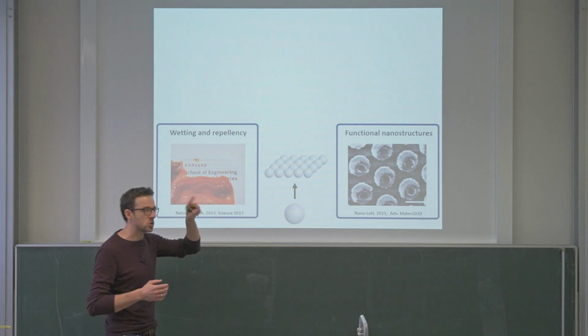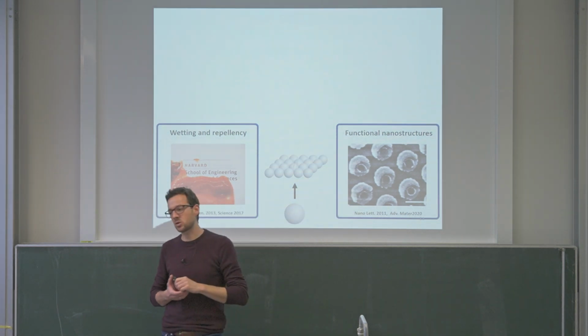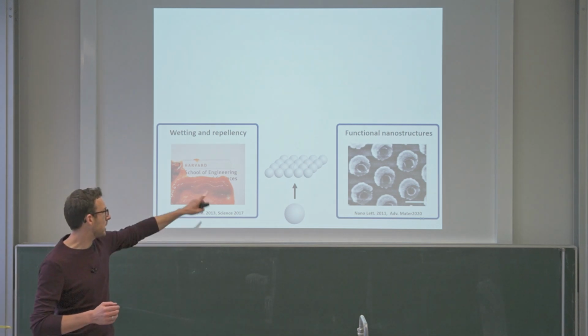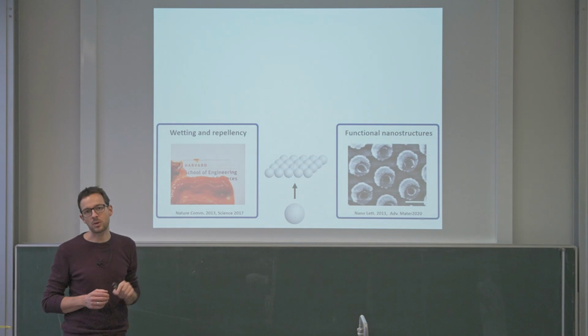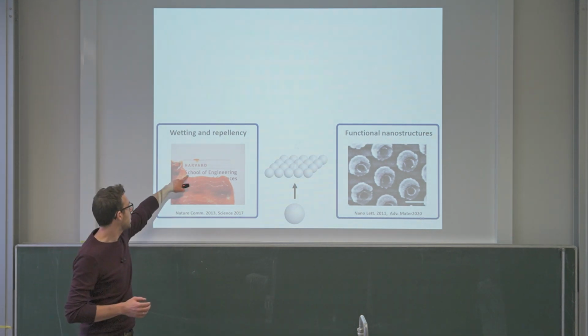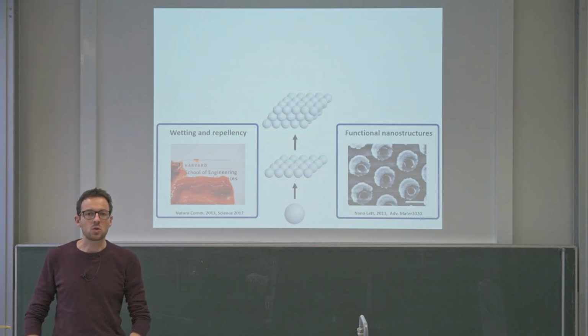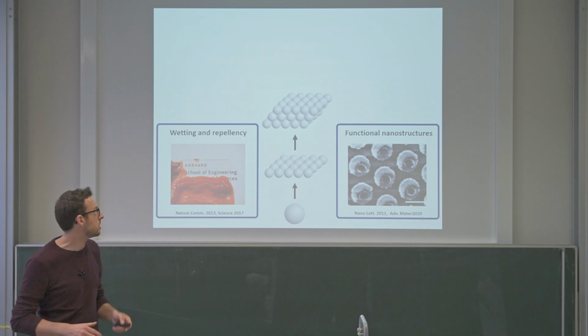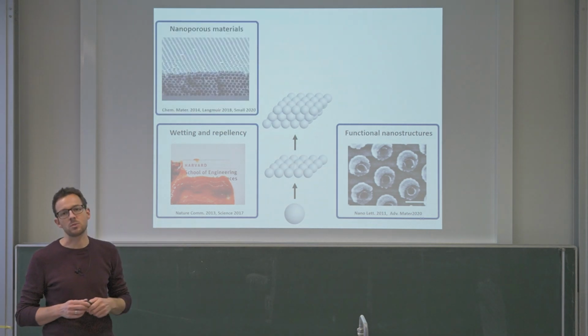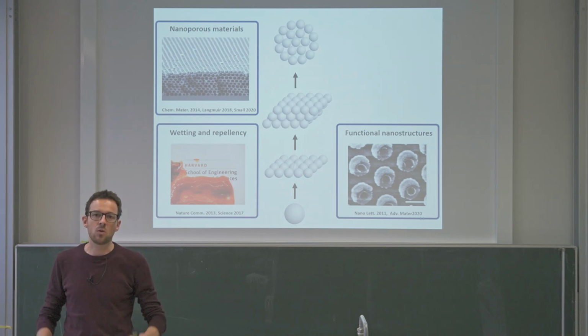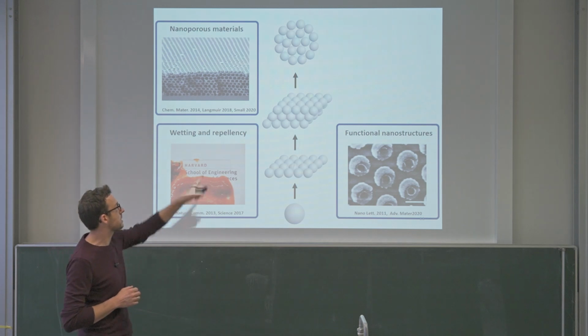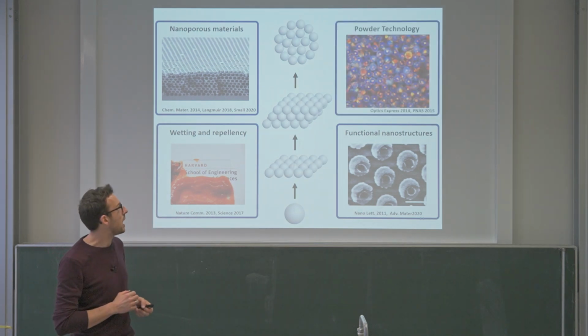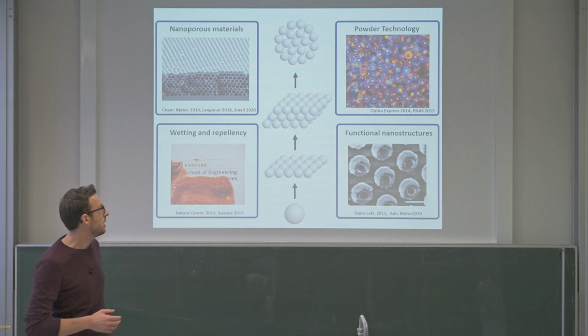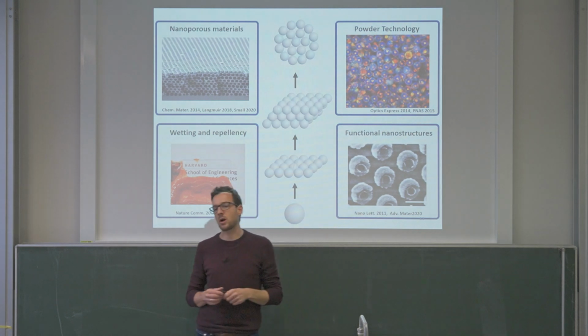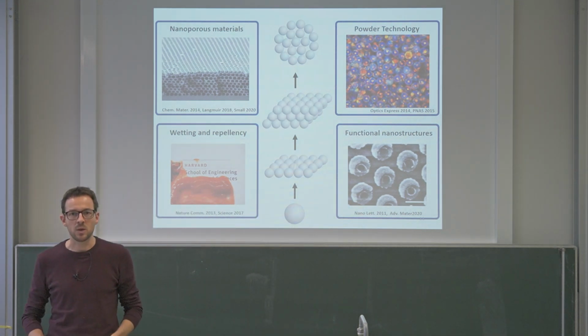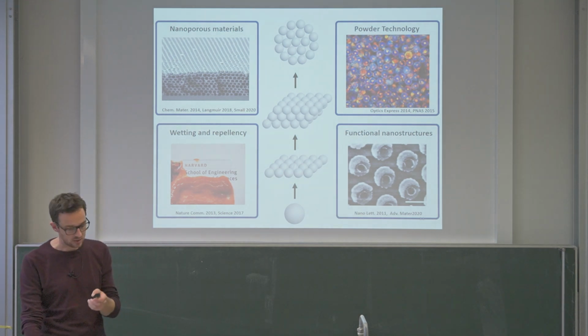So we can either use this to further shape our substrate and then create functional nanostructures that can have very interesting optical properties, or we can make rough surfaces to tailor the wetting properties and especially make repellent materials, as you see here with the ketchup that flies down. Well, then we can also go into 3 dimensions. We pack more and more spheres into a 3-dimensional crystal, and automatically we get nanoporous materials. And then we can also go away from a surface and look at confined space, which is scientifically very interesting. So how do these spheres pack in a spherical confinement? And then we can get access to superparticles that can also have interesting properties. Here you see, for example, a structural color pigment that has color that simply comes from the periodic arrangement of the particles within this superparticle.